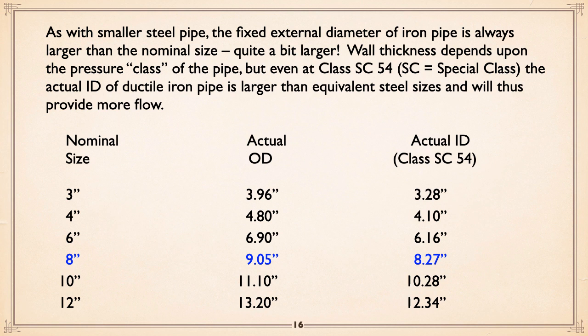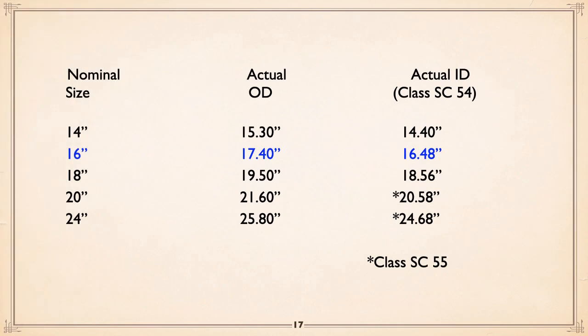4 inches, 4.5 normally. These are 4.8 OD, and at SC54, ID is 4.1. So you can see the numbers as you go along. It is like 12 inch instead of being 12 3/4, actually 13.2 OD, and the ID, instead of being around 12 inches, 12.34. So you do get more flow out of it. These are into the larger sizes. At 20 and 24 inch, instead of SC54, you need to go to SC55.